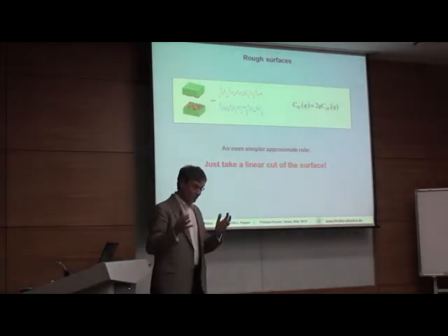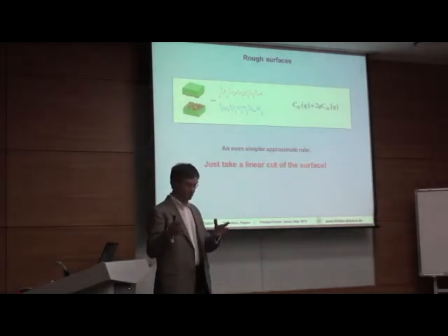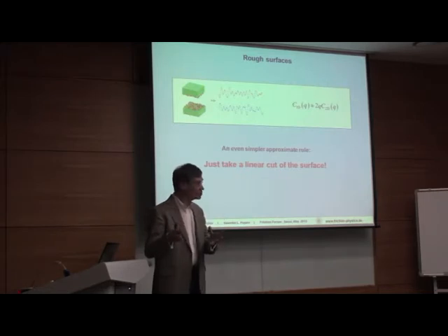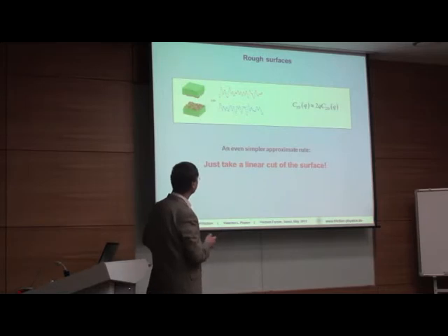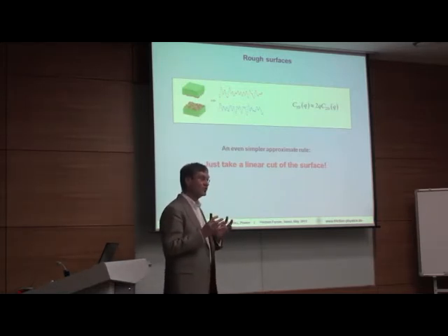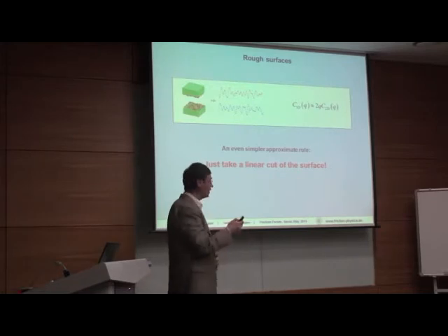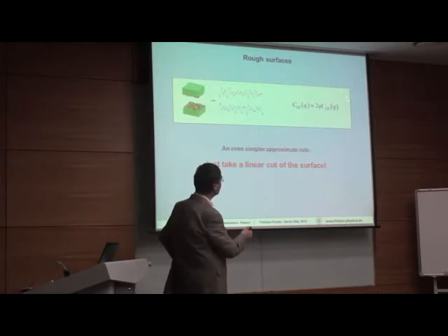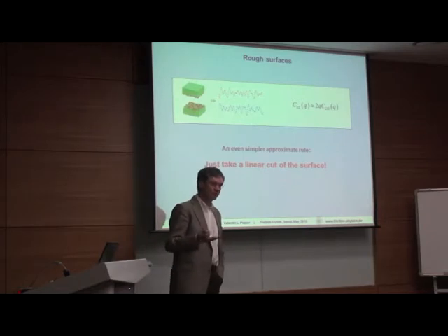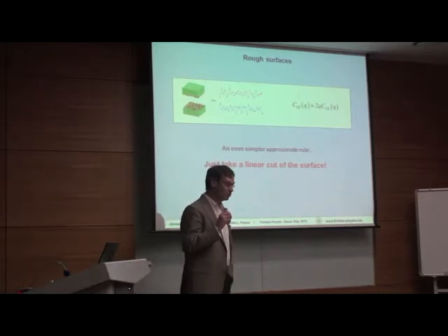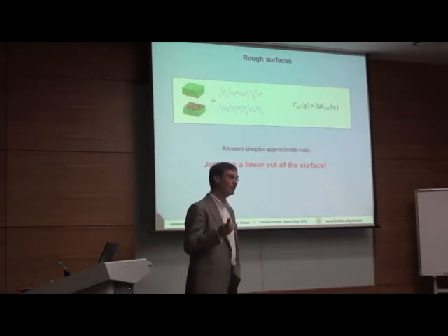Of course, again, one has to replace the three-dimensional rough surface by a one-dimensional substitute surface. The rule is formulated in terms of the spectral density of the surface. If you have the two-dimensional spectral density, the square of the Fourier components as a function of the wave vector, then you multiply it with 2q, and then you have one dimension. It is the approximate rule.